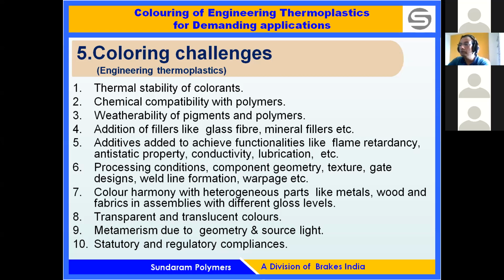Processing conditions, component geometry, texture, gate designs, weld line formations, warpage issues. Sometimes the color, when molded in the standard flakes, matches very closely, but because of the geometry and the weld lines appearing on the component, the color tends to deviate compared to the masters. So we need to consider the geometry, texture, and the gate designs, where at least the gate should be avoided near the edge surface of the article.